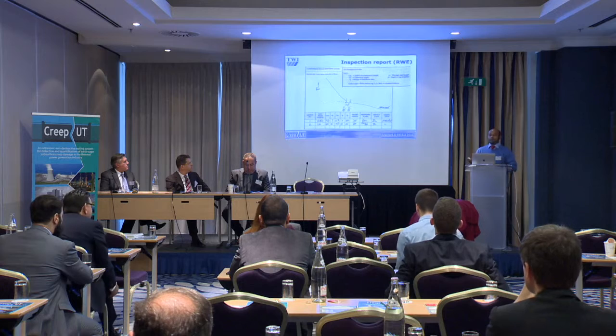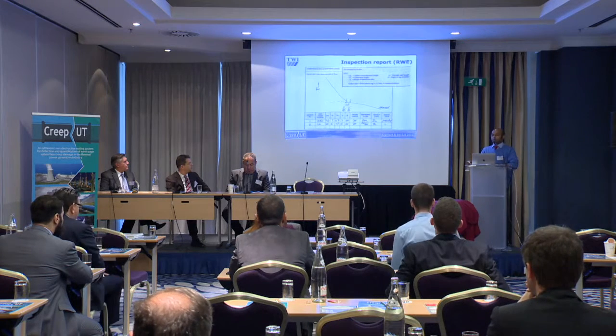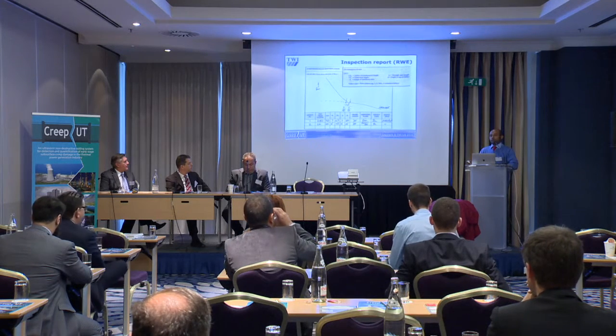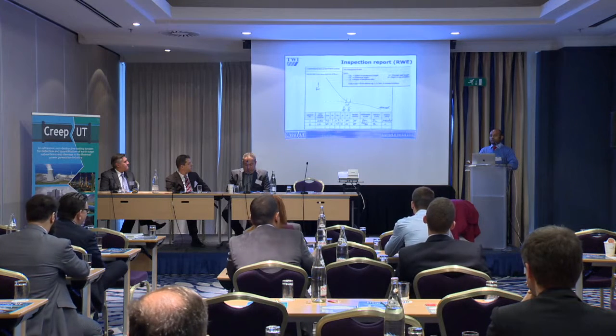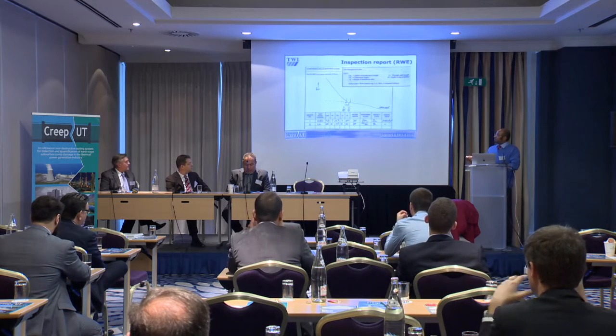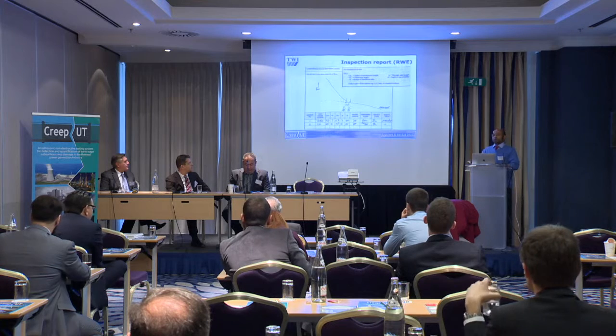So methods such as magnetic particle inspection, dye penetrant inspection, replication, and so on are relatively insensitive to these types of damage until it arrives near the surface. So the aim was to try and detect this kind of damage before it turns into a crack and while it's subsurface.